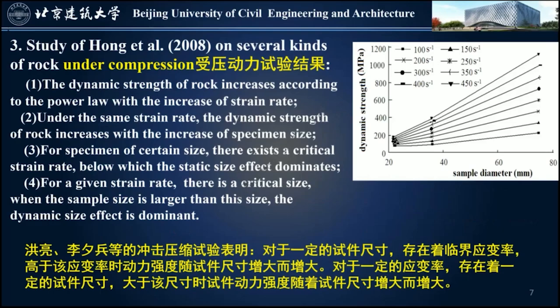Study of Hong et al. on several kinds of rock under compression revealed that the dynamical strength of rock increases according to the power law with the increase of strain rate, and at the same strain rate, the dynamical strength of rock increases with the increase of specimen size. For specimens of certain size, there exists a critical strain rate below which the static size effect dominates. For a given strain rate, there is a critical size. When the sample size is larger than this size, the dynamical size effect is dominant.